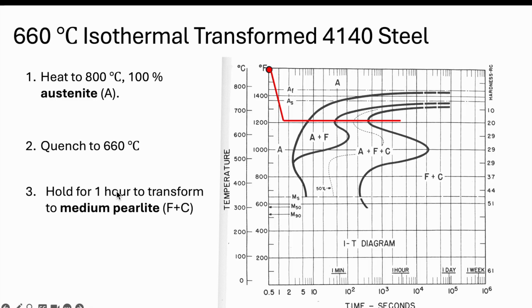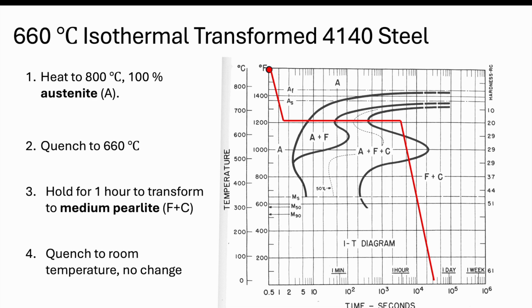So this is again going to be pearlite, and like I mentioned in the previous slide, the layer structure can vary with temperature. So as we go up in temperature, the layers get thicker, and so we're going to call this the medium pearlite because it's kind of in the middle of this temperature range. So we get medium pearlite, and we'll still have the ferrite phase as well. And then a quench to get down to room temperature.